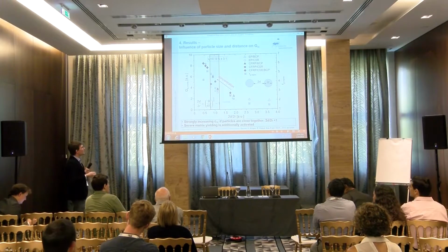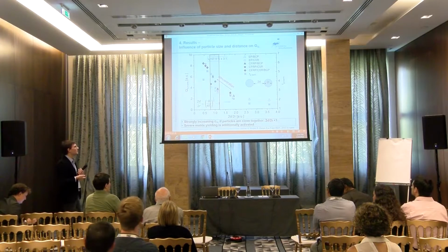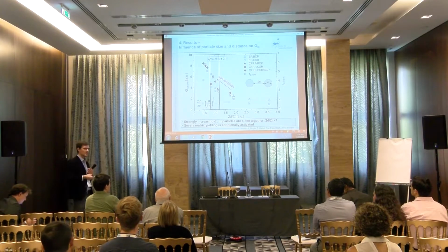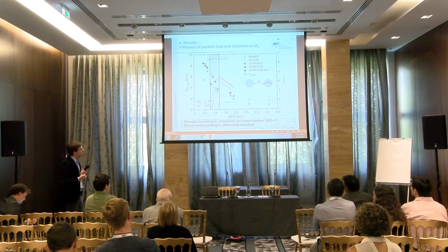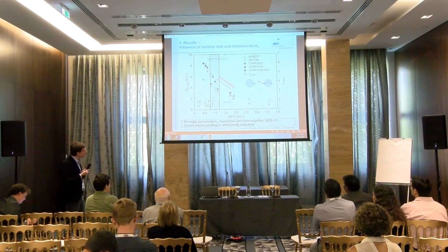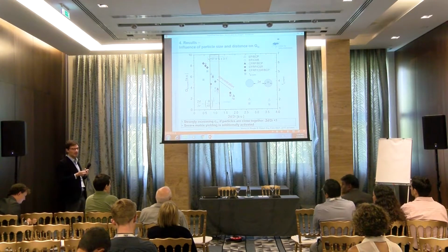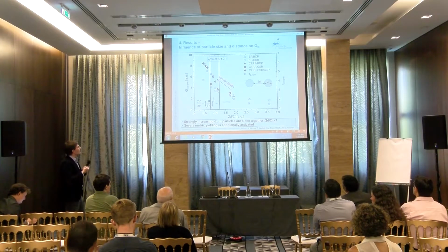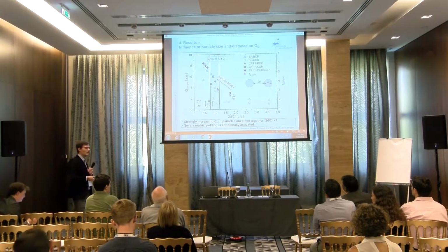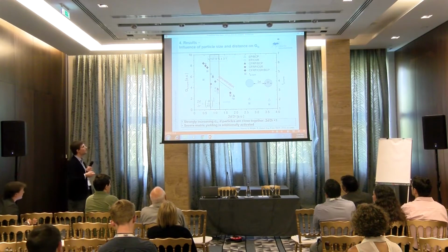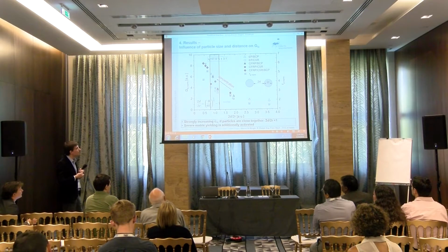To have a small digression on the micromechanics, we took a look at the particle distribution, the particle size and the interparticle distances in these laminates. And what we found is, first of all, on the x-axis you have your interparticle distance divided by the particle radius, right? So a ratio of this one to that one. On the y-axis you have your energy release rate. So the smaller you make the interspacing between the particles, the higher your energy release rate becomes.